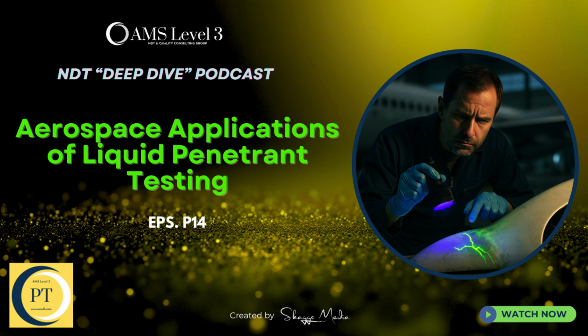First, the ultrasound physically helps shake loose and flush out those trapped contaminants. Second, it flushes the interfaces clean. And third, and most importantly, it rapidly deposits the fluid deep into the crack, which minimizes the required dwell time. You're force-feeding the penetrant into the defect. So you're going from, what, hours to just a few minutes? The time reduction is staggering.